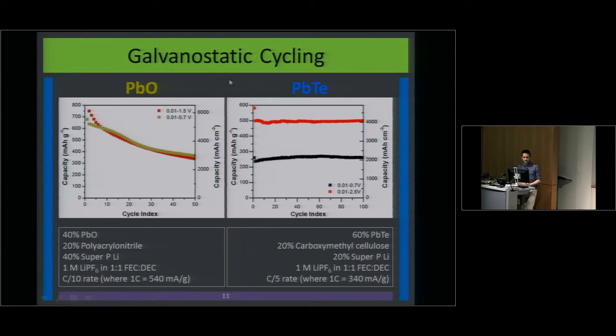You see that the lead oxide has pretty rapid capacity fade, so we want these lines to be as straight as possible. In an ideal battery, it would be perfectly flat for thousands of cycles. You may ask why I only have 100 cycles—I could do 1,000, but I would be here for many more years than I would like to be. So 100 cycles is kind of enough to show that, hey, this deserves further research.